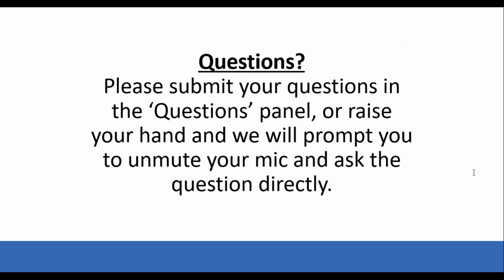Thank you. Annette Larson has asked as well, we have a polymer system that goes through TG, swelling and probably water clustering. How can we separate these events in the best way? So I think if you already have a TG value, then if you perform the experiments, just get a quick scan with the ramping method, then you can also get a TG humidity for the sample at certain temperatures. And if you want to get good quality data, then you can set up the step method with smaller steps, like 5% step or even 2% step. Then you can see at exactly which percent of humidity the sample goes through this kind of phase change. And if you want to measure any property of the sample, like the BET surface area of the material, you need to avoid those phase changes. Just measure it before the phase change of the humidity of the sample.